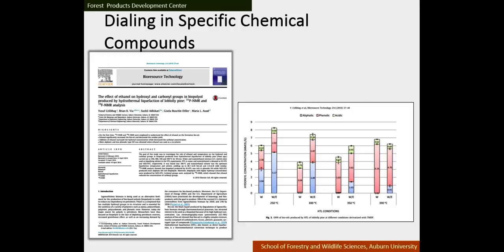And what we have found is that when we use different temperatures for liquefaction, we get different hydroxyl groups. And when we use PNMR, we can actually separate the hydroxyl groups, whether they're aliphatic, phenolic, or acidic. And so we can look at where the OH groups are coming from.